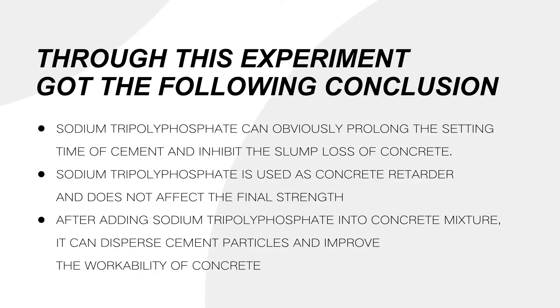Through this experiment, we got the following conclusions. 1. Sodium tripolyphosphate can obviously prolong the setting time of cement and inhibit the slump loss of concrete.